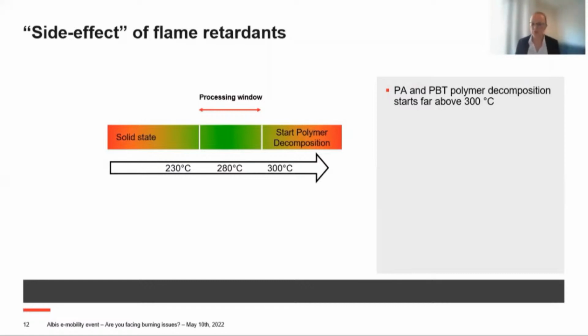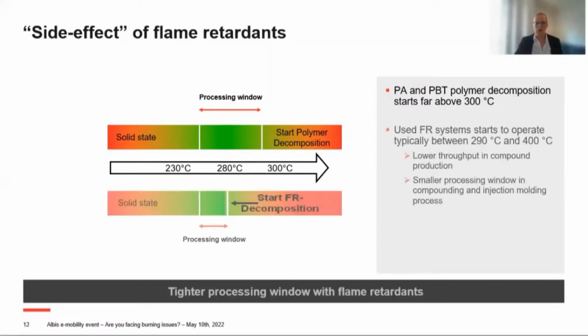However, in polyamide and PBT without flame retardants, the decomposition starts way above 300 degrees Celsius. So you have a pretty wide processing window. However, as soon as you incorporate flame retardants in your system, you limit the processing window. Because typically, especially halogen-free flame retardant systems start to operate between 290 and 400 degrees Celsius. And that means that you always have to make sure that your material stays below 290 degrees Celsius, even in processing. That means in the end that when you use flame retardant materials, you tighten your processing window.